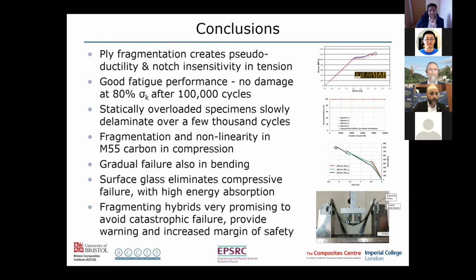Very good. Thank you, Michael. We have a question from Vivek Singh about the dynamic effect. Did you test these hybrid composites under dynamic loading, and how does the response evolve with the dynamic effect, due to the viscoelastic response and the rate dependent effect? For these types of material, we have done some high-speed tests, and there is a paper on that, which I've not included here. We found that for these hybrids, it doesn't make very much difference, because the fibers are not very rate dependent. Glass ones perhaps a little bit, but the carbon are not very much. We see that we still get this same fragmenting mechanism under high rate loading as well.